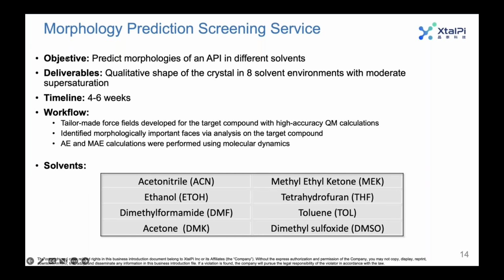In this case, the objective was to predict the morphologies of an API in different solvents. The deliverable was the qualitative shape of the crystal in 8 solvent environments, where moderate supersaturation was simulated in each case. The timeline for these projects is about 4 to 6 weeks, depending on the size of the system and the complexity of the simulations. That's for tailor-making the force field, so parameterizing a force field, and also performing the molecular dynamics simulations, plus the data analysis and workup.